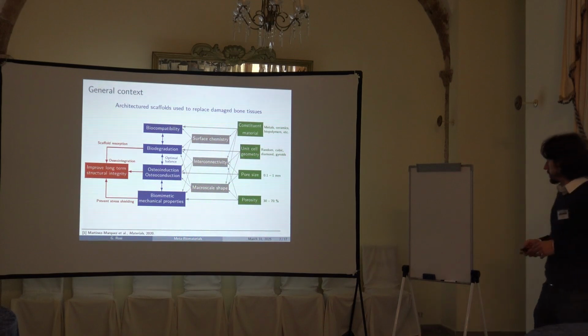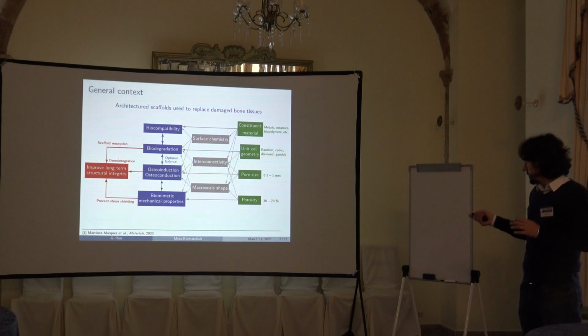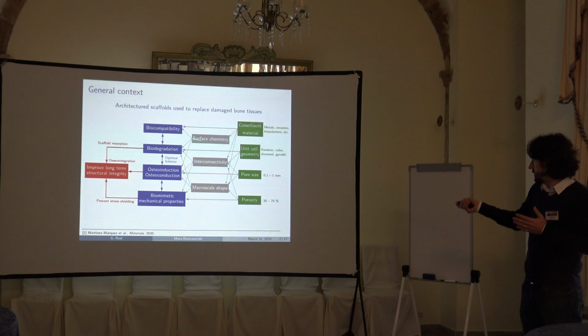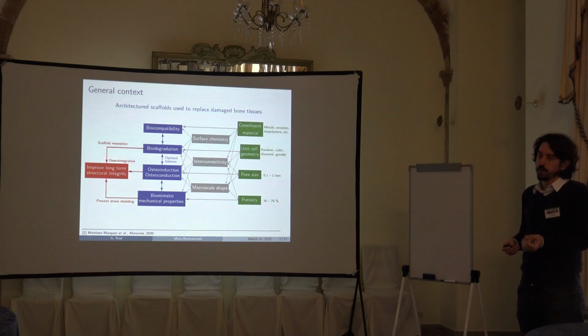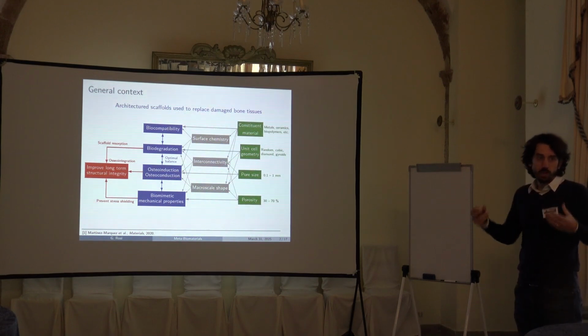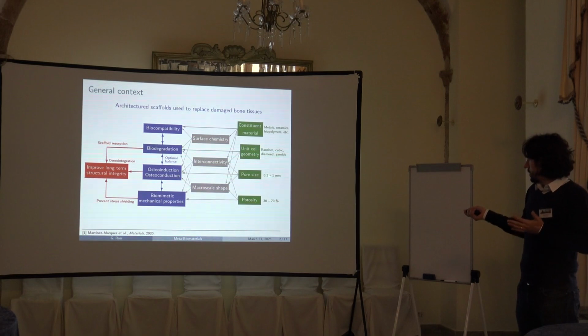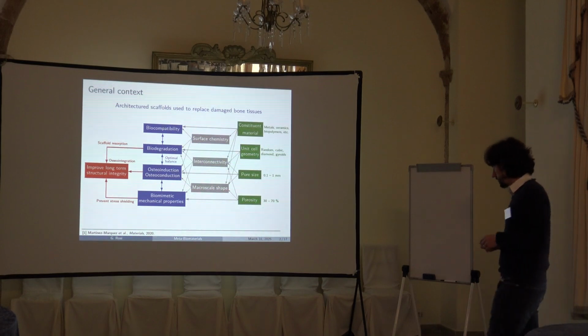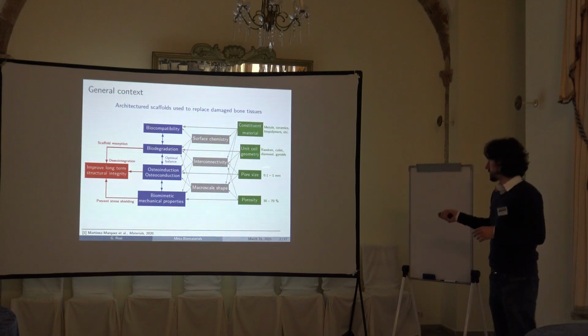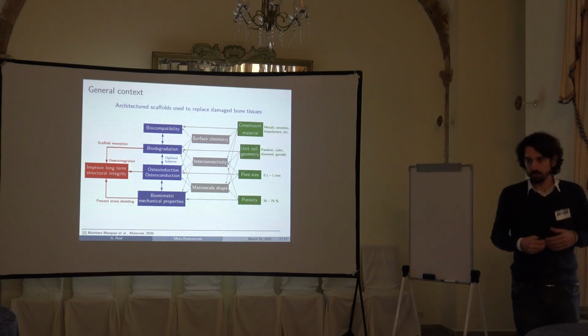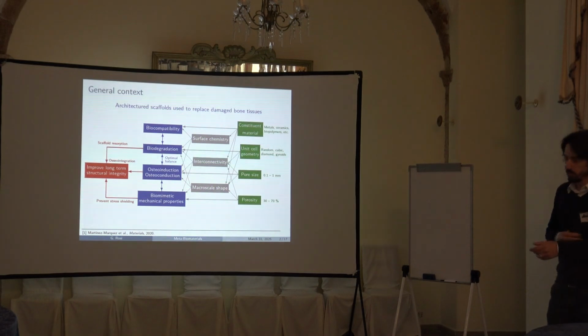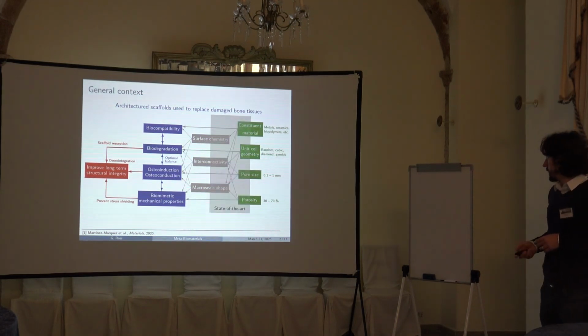Cubic, diamond, gyroids, TPMS in general. What is important is the pore size needed to have these properties and promote osteoinduction, for instance. You must not have pores that are too small, nor too large. So it's around 100 microns to millimeters, and the porosity is between 30 and 70%. This is to replace what is called sponge bone, trabecular spongy bone.